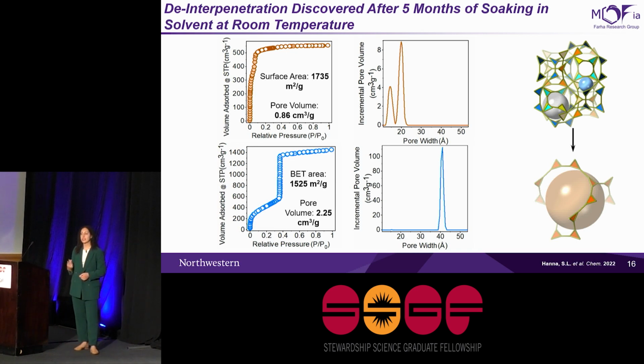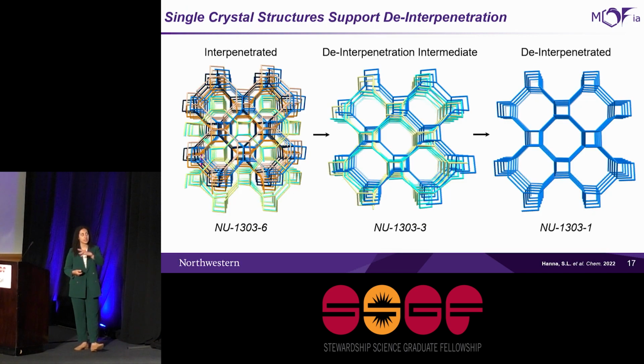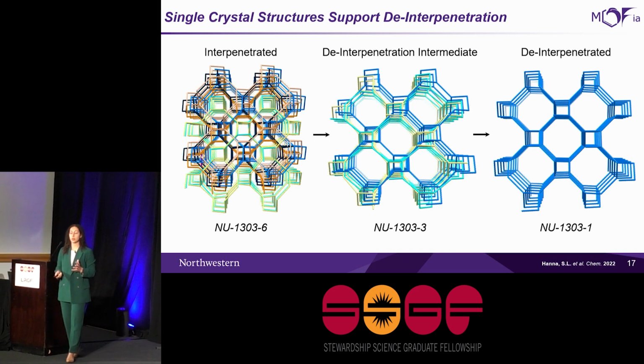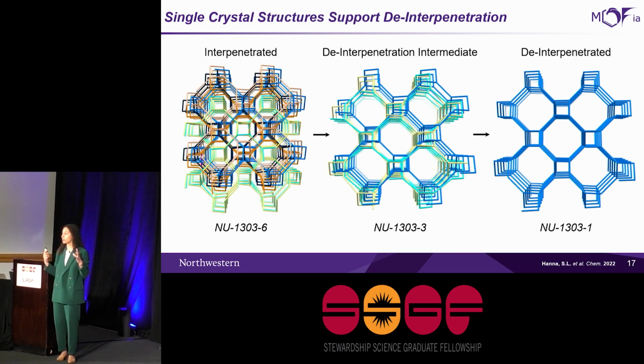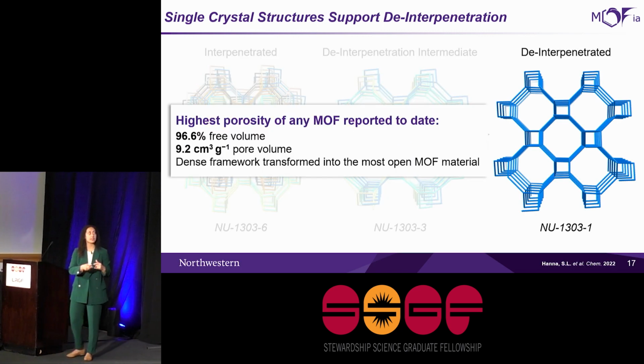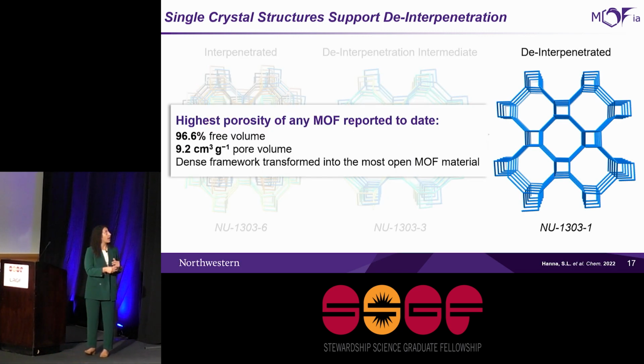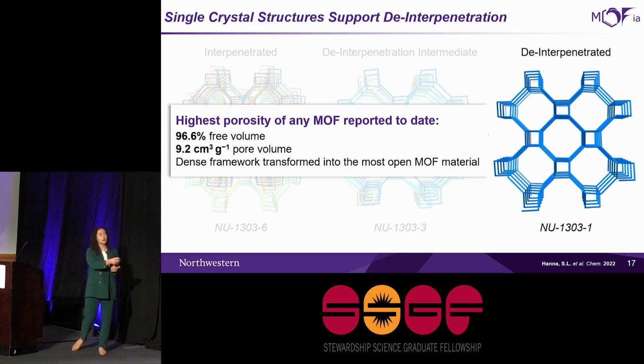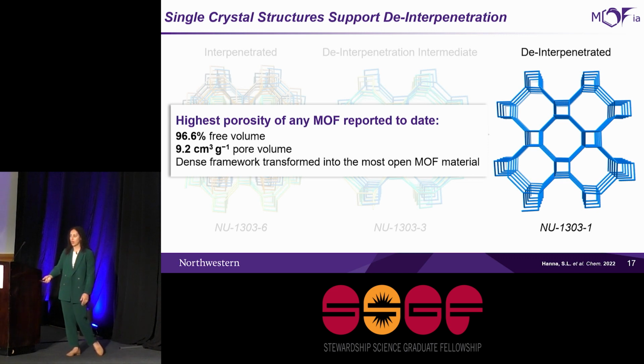And so going forward, I collected single crystal structures of this process as it was occurring. You can see this is a version of the 6-fold, a 3-fold, and then a completely non-interpenetrated MOF. So it's really cool to get to capture this in real time and see that this structural transformation was actually occurring. But what's more interesting is that this final non-interpenetrated material actually holds the record for the highest porosity of any MOF that's been reported, where you have over 96% of its volume being totally empty. So that really begs the question, how are we getting this super open material from a material that was originally really densely packed when we know that this process is reportedly not favorable?